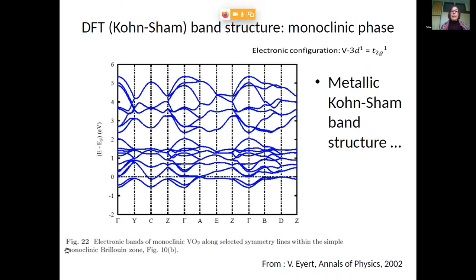So we take now the other crystal structure, and again from Volker Eyert, same setup, same calculational framework. And again, you have here now the t2g states, Fermi level is at zero, and you see that there's one band which is close to being split off, but not completely. So the Kohn-Sham structure here would look metallic, but it is obvious that it's not very, very far from an insulating configuration.